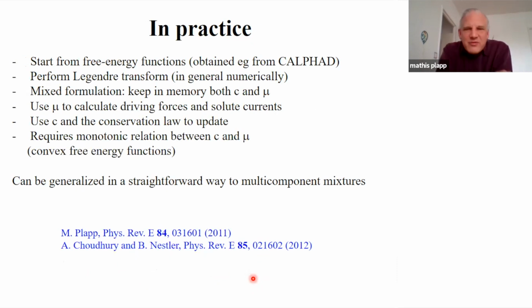And so now, if I want to use this in practice, how do I do that? Well, the starting point should still be free energy functions that I can obtain, for example, from a CALPHAD database. Then I need to perform the Legendre transforms, and it is generally advantageous to use what I call a mixed formulation. That is, I keep both c and mu, and then I use mu to calculate the driving forces for phase motion and the solute currents. But I keep c for updating without any errors the mass conservation law, which ensures that I get good mass conservation.